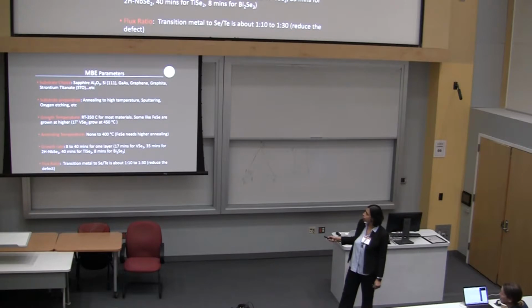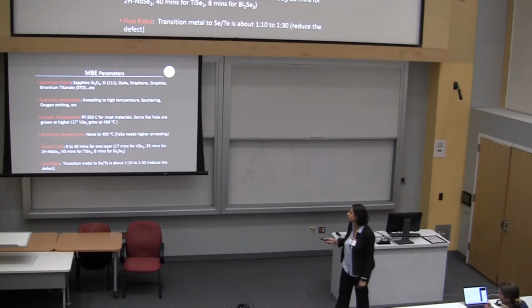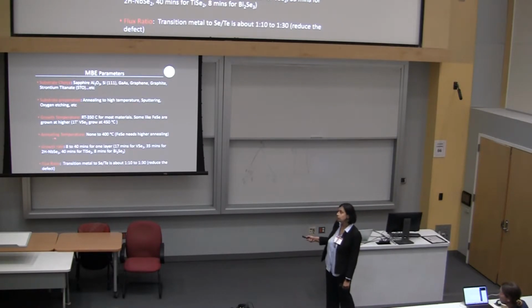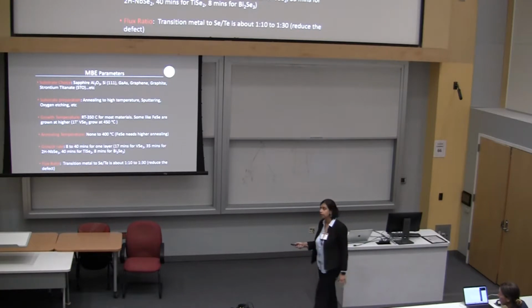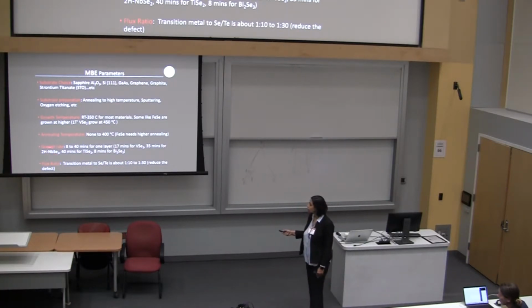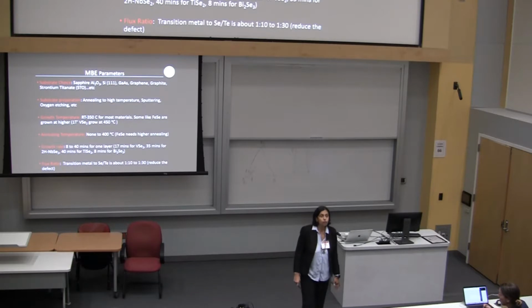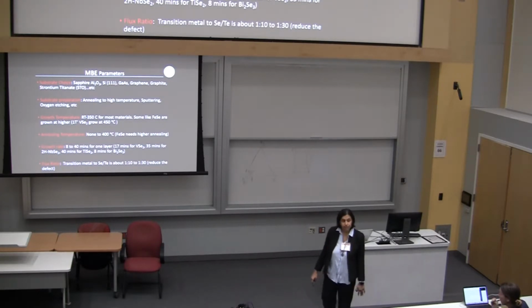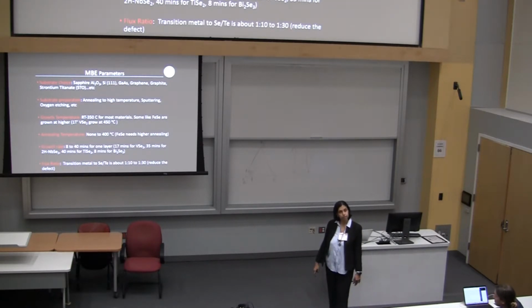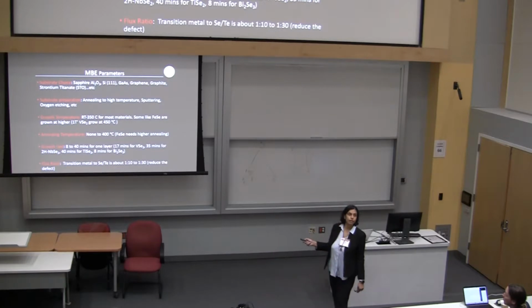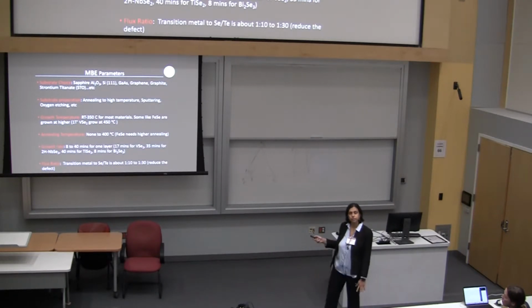And after you grow, you anneal. And typically you anneal at a temperature that's slightly lower than the growth temperature. Sometimes you skip this step, but most often you anneal. The growth rate is really important. We grow really slowly, but sometimes if you grow too slow, then the film will not grow, so you have to sort of play around with this. And finally, the flux ratio. Like Judy was saying, sometimes you have to really bombard the material with the chalcogen.